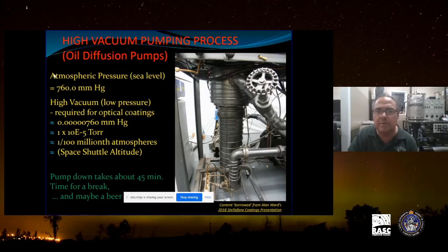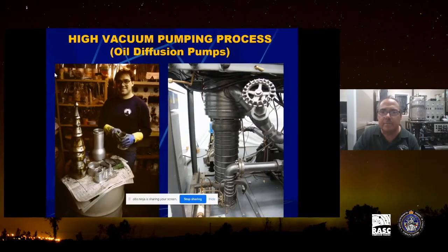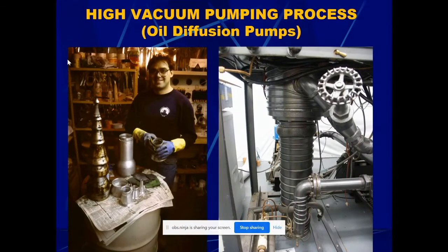But the actual coating actually takes very, very little time. It only takes maybe a couple of seconds for the aluminum to vaporize. It's done in a split second. The other coatings, like magnesium fluoride and cerium dioxide, may take up to several minutes to coat, and that's nice because you need to monitor the thickness as you're depositing those materials, in order to get the proper enhancement that you're looking for.